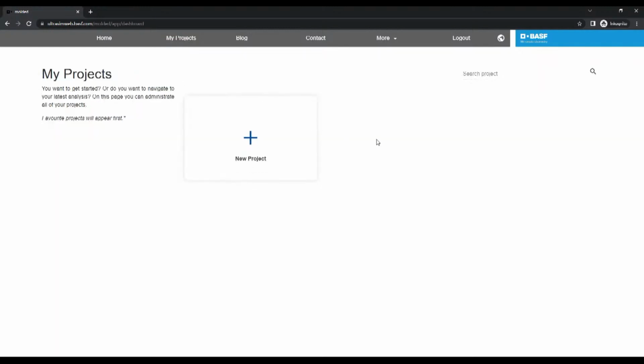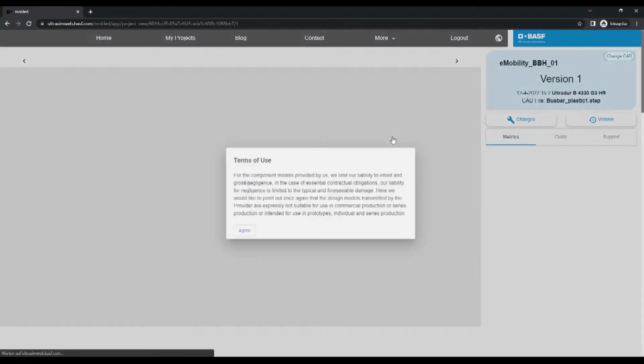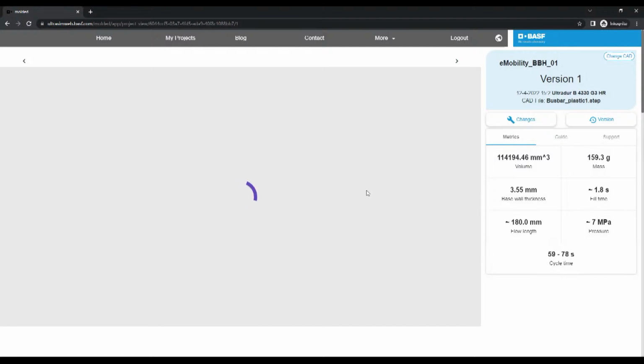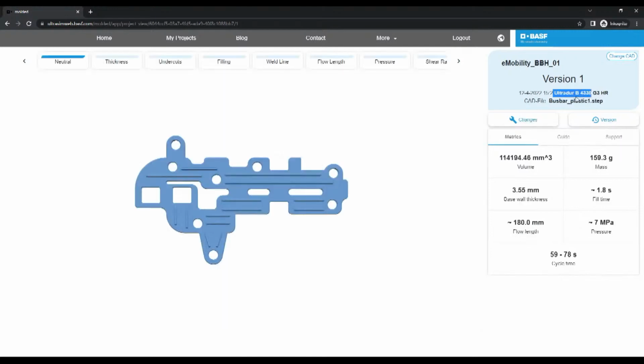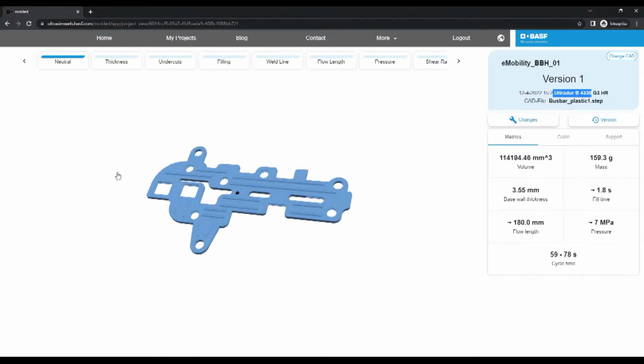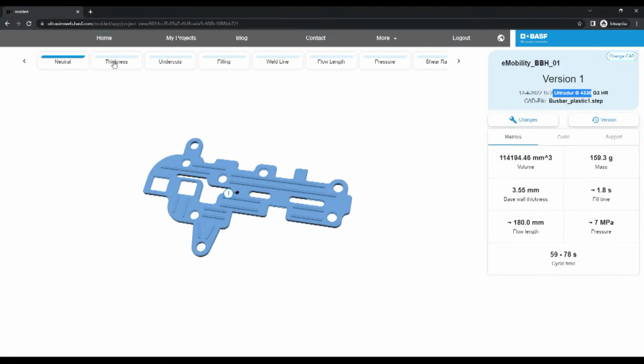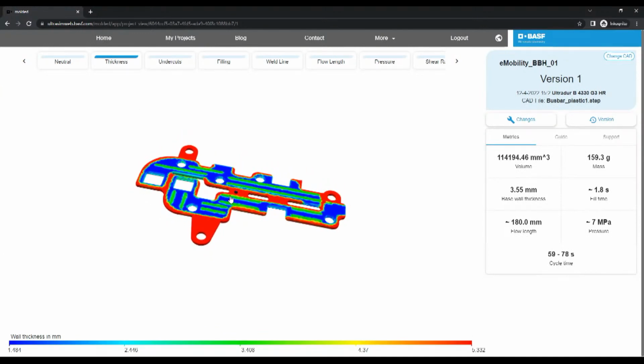I will not do that because I have already prepared a project for this purpose. I have uploaded a part design of a bus bar holder and I have chosen the material Ultradur B 4330 with a glass fiber content of 15%. And here we can see now the part design. I have now the opportunity to check out the part design and check out some visualizations, for instance, the thickness of the part. And here we can already see that there are some red areas, very thick areas of the part, which most likely will also lead to very high cycle times because the melt needs to cool down before demolding.